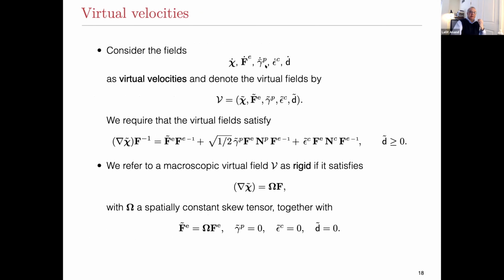So these were my kinematical fields, and I'm going to treat them as virtual velocities to figure out what the basic balance laws are. So instead of chi dot, I'll write chi tilde for a virtual velocity, f tilde e for a virtual f dot e, and so forth. And those virtual quantities have to satisfy the same kinematical constraints that we had previously. I'll need one other notion, and that is that of a rigid virtual velocity field. A rigid virtual velocity field is essentially one for which there's no plasticity, no crazing, no damage. Basically the velocity gradient is omega, which is a skew tensor, times f, and that omega is spatially constant. So it looks like a rigid rotation, or a rigid spin.